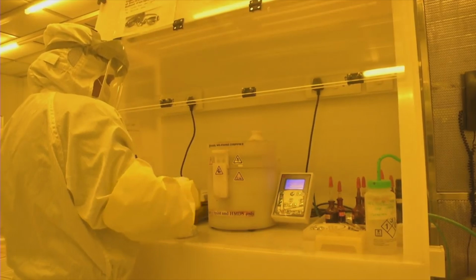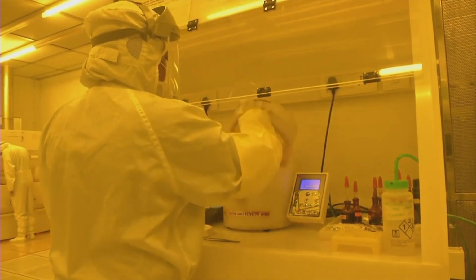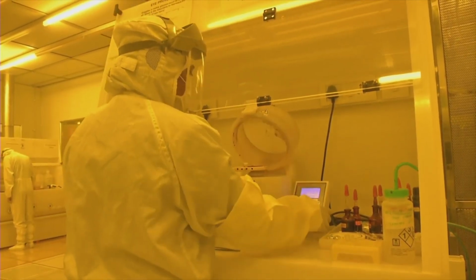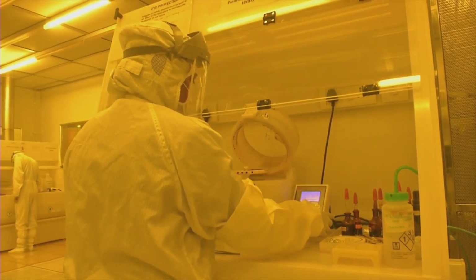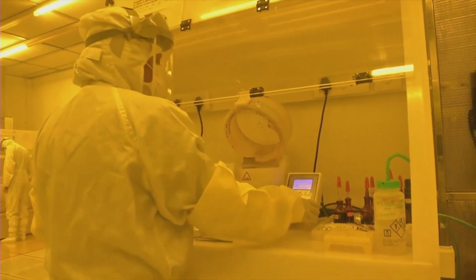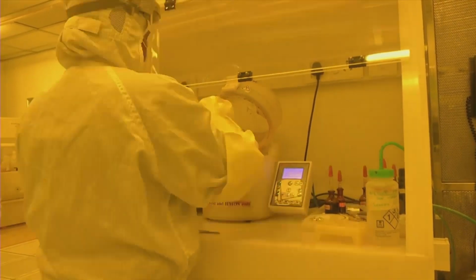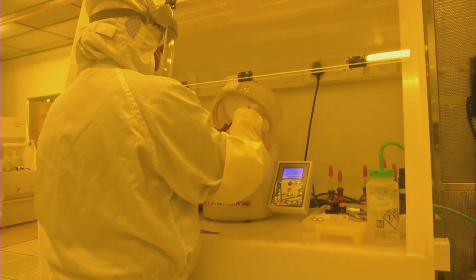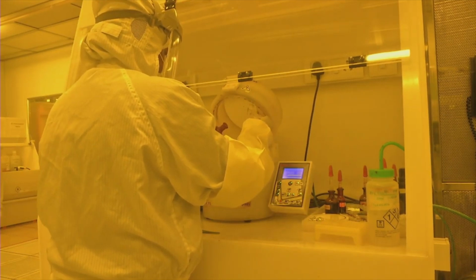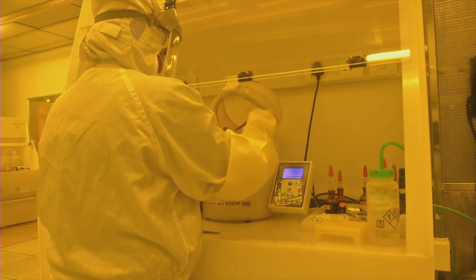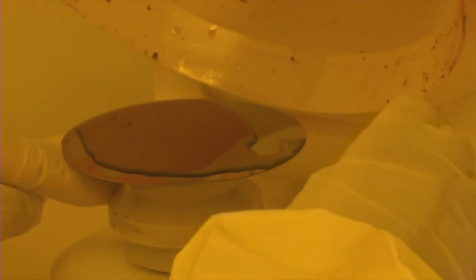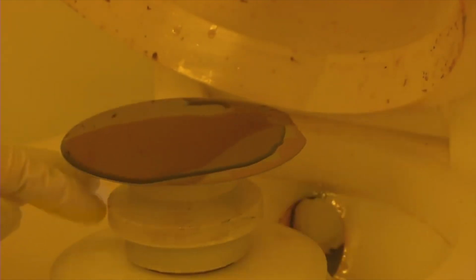So the wafer is put on the spinner. We use spin coating of the photoresist. We are going to place the wafer centered in the spin coater, and then we have to select the appropriate program for rotation. And before that, we will drop cast the photoresist. You can see here a sufficient amount of photoresist is coated on the wafer, and after coating it, we are going to spin it.